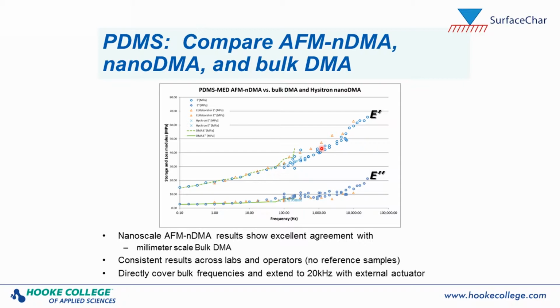And notice that the frequency range that is covered by AFM nano DMA, which again are our blue points, goes here from 0.1 hertz all the way up to 20 kilohertz, which is a very high frequency, but in general a very large frequency range with the AFM nano DMA. Again, I remind you that the bulk DMA measurement in green is a much smaller frequency range from 0.1 hertz to approximately 300 hertz.